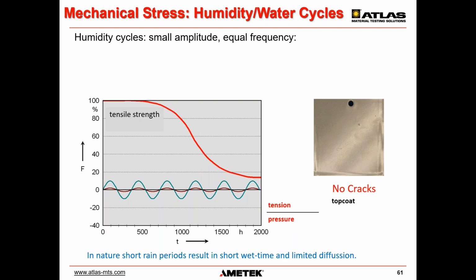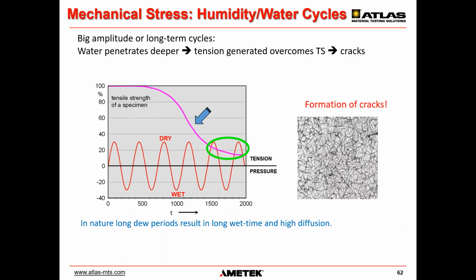also acid resistance. Weathering test methods were developed 20 to 30 years ago, first only in a climate chamber with water, without irradiance. Theoretically, cracks are generated when the humidity cycle has such a large amplitude to exceed the tensile strength after a certain point. Here in the trial, it is not reached in this one here. No, this amplitude is not enough.